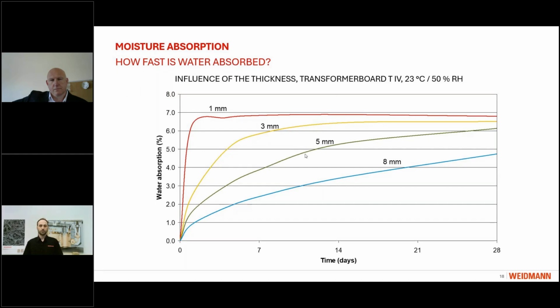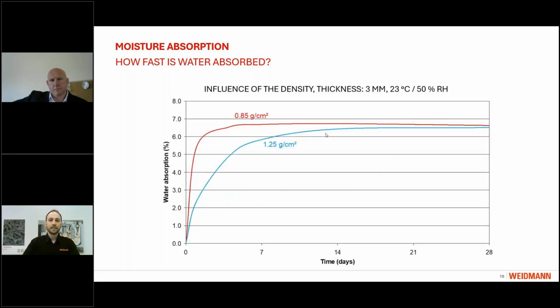So here we can see a graph that shows you the influence of thickness with regards to water absorption when we expose them to 23 degrees Celsius and 50% relative humidity. You can see that the thicker the board, the longer it takes for it to reach equilibrium condition. Similar to this, we can see that at the same conditions, a board with 3 millimeter thickness will have a faster equilibrium moisture content at lower density compared to high density material.